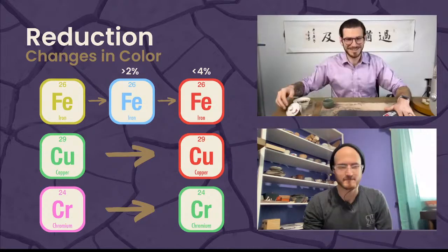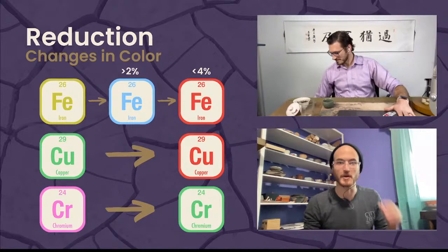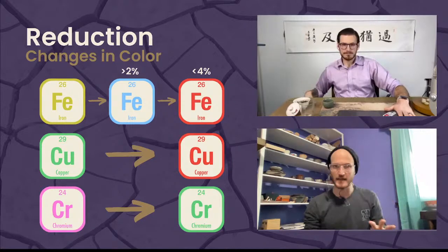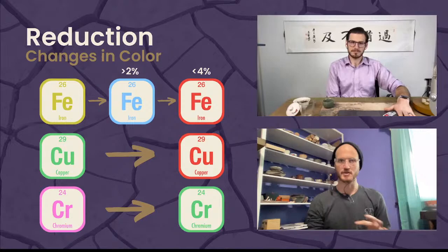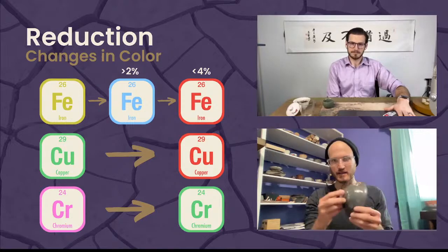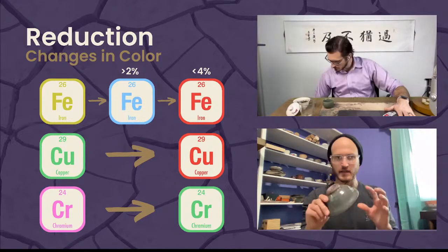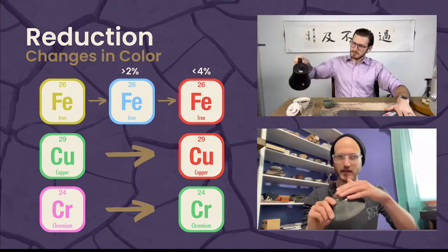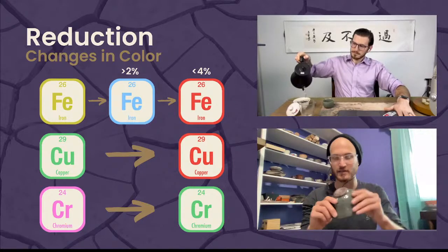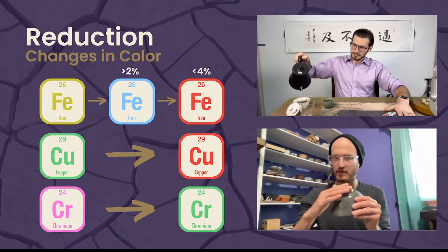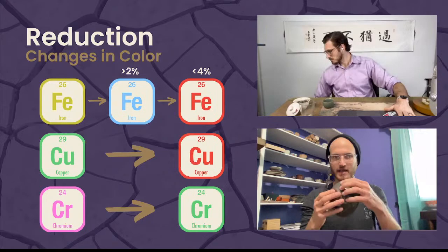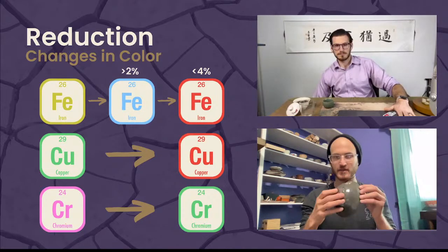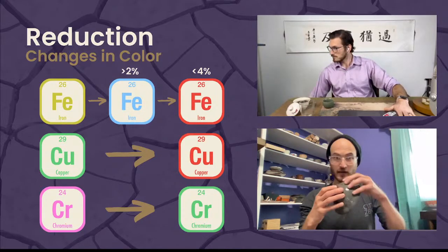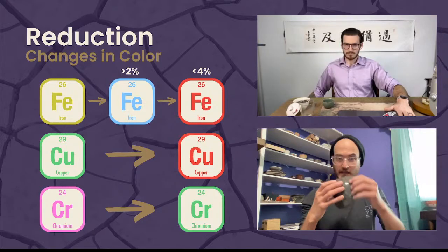So now we're talking about glazes. Before we were talking about clay and the way that reduction interacts with clay. Now we're talking about glaze. So when you have oxides suspended in a glaze, you have a totally different effect than when they're trapped inside of a clay, because there's really only so much mobility and interaction they can get. It's mostly on the surface. But with glazes, because they get totally molten and melted when they're firing, the atmosphere of the kiln gets to interact with every layer of the glaze.